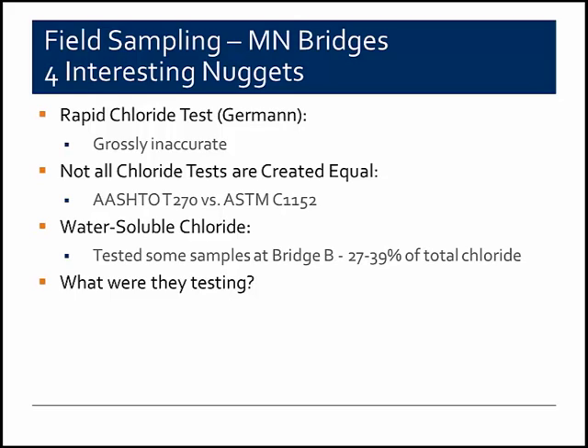But in the event the test is considered for other kind of quick and dirty chloride content analysis, I would have some hesitation about that, at least based on my experiences and the results we obtained in some of the field sampling work here, particularly with respect to SikaGrout and its chloride content.